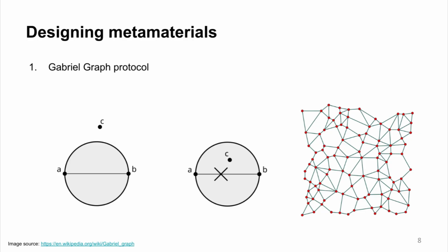And once we have such a point cloud, we could have multiple different protocols of connecting them. In the Gabriel graph, we consider a pair of points at a time, and we decide whether to connect that pair depending on whether the circle whose diameter is the line segment connecting the 2 points includes a third point in its interior. If there is a third point in the interior of that circle, then we do not connect those 2 points. However, if there is no other point in the interior of the circle, then we do connect those 2 points. And a sample network generated by using such a protocol is shown in this graph on the right.